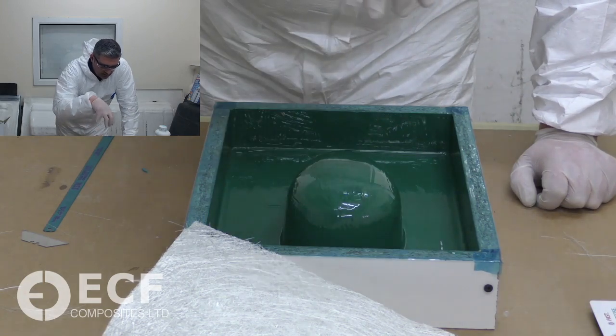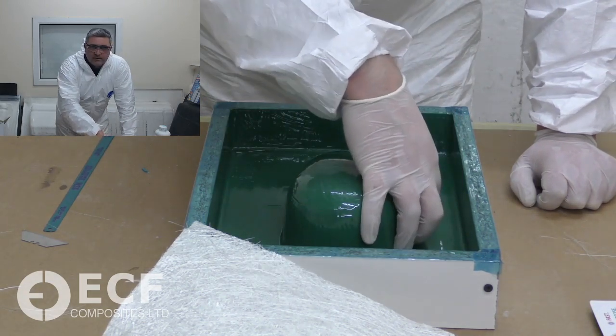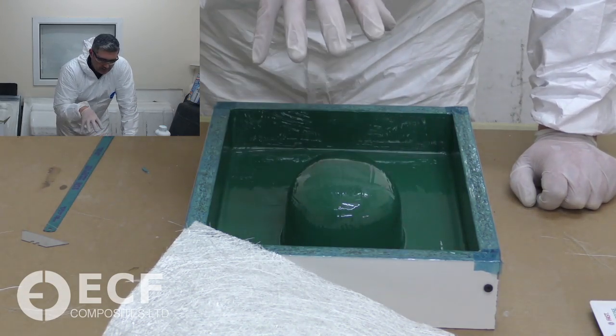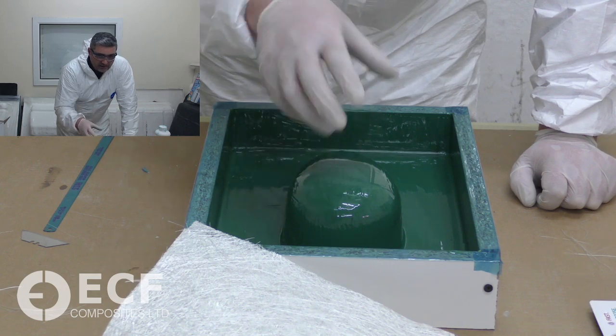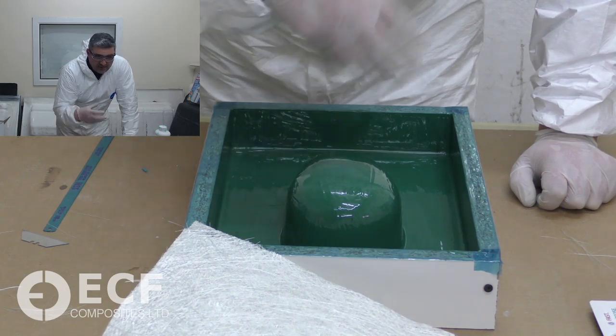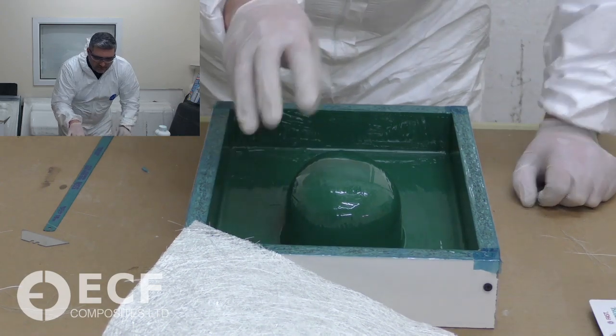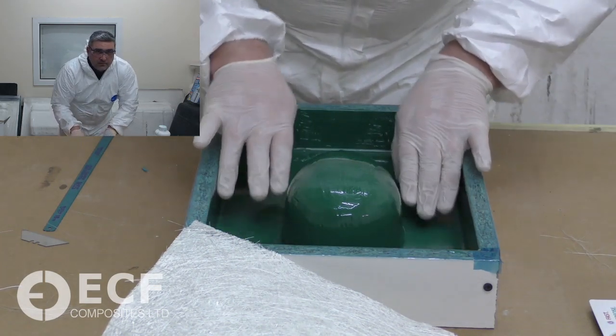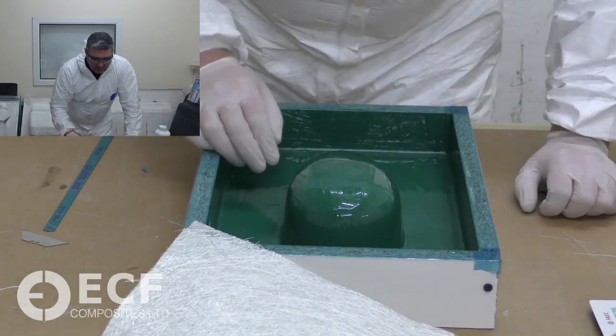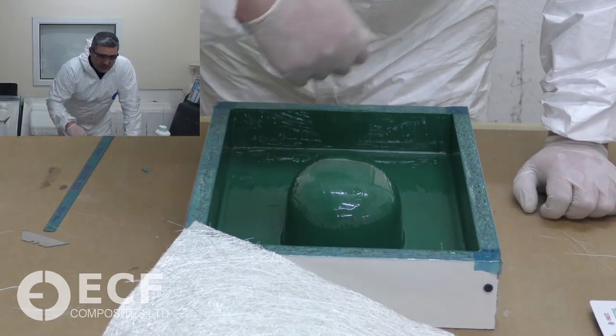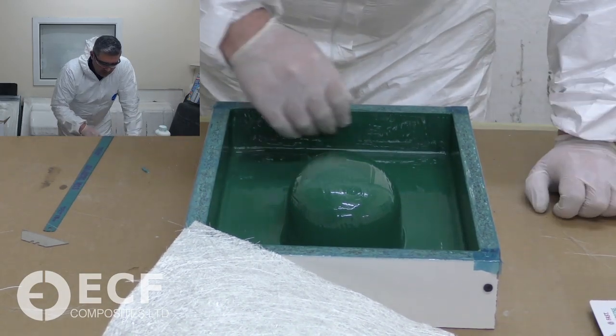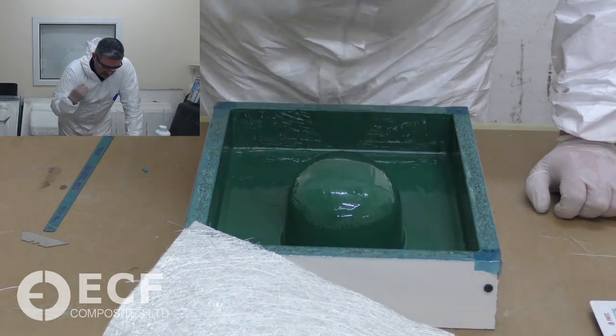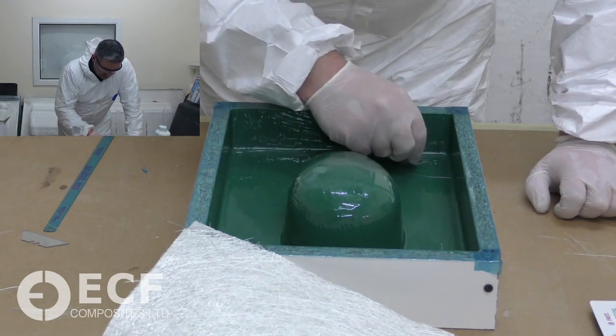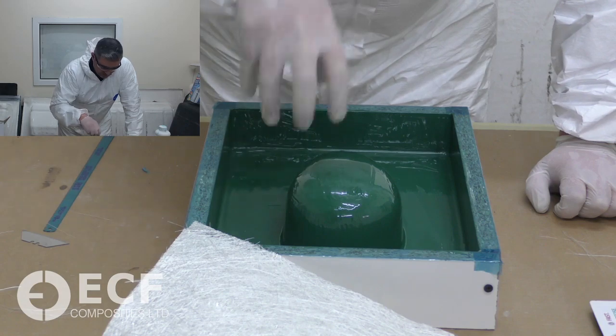The reason the lower areas of the mould take so long to cure off is because the product contains styrene solvent. Styrene's heavier than air, and sometimes the vapours just lie in the bottom of the mould. So sometimes you need to blow it out, or just tip the whole thing upside down once it starts to cure, and that'll get rid of the styrene and help the deep parts of the mould cure quicker.